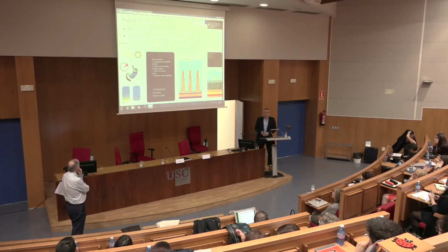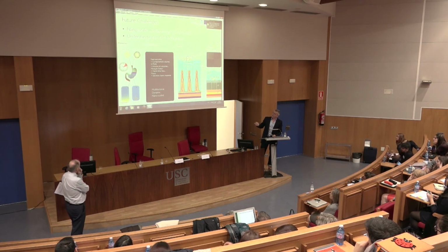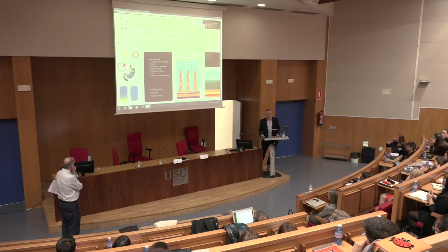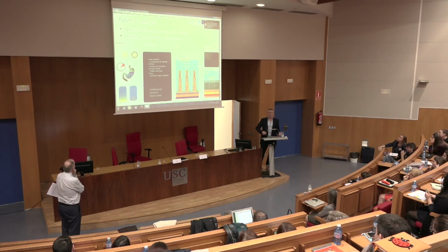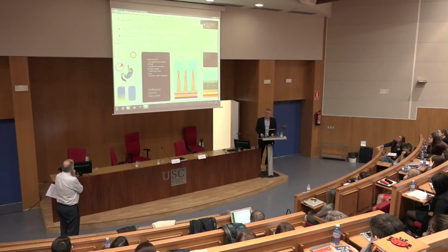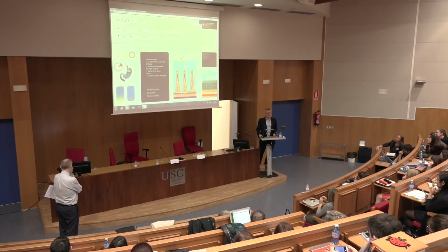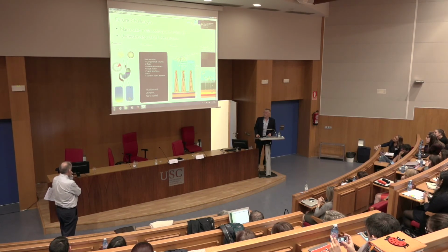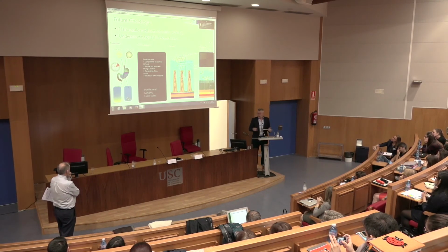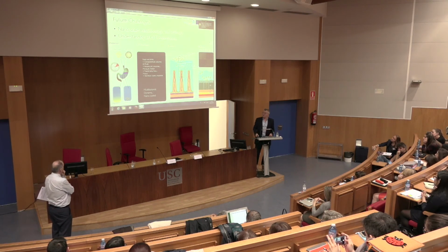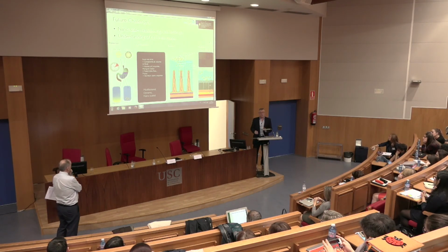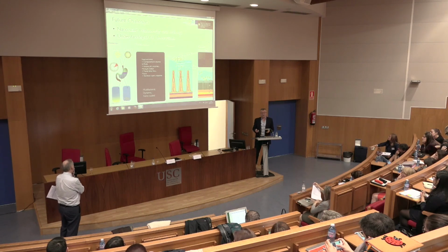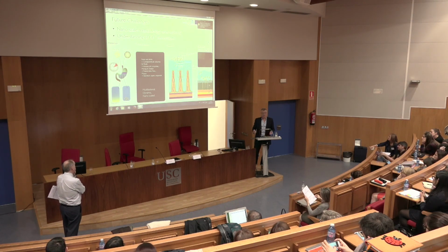And then ultimately, I guess we'll hear more about this, we found that we have prototypes that work. And this is what my key learning is really, where I say this was naive. Ultimately something that's very difficult to capture, and where we do not know what is important and where we have to go through what we've learned now and reassess, is the whole interaction of nanoparticles in the GI tract. The mixing, we have different pHs, we look at different species, they have different pH gradients. If you look at the array of different simulated gastric fluids or simulated intestinal fluids, they all differ in some components. They may seem trivial, but if you have cholate in there or not, it will make a difference. And that's something where we need to understand a lot more about how to simulate that.